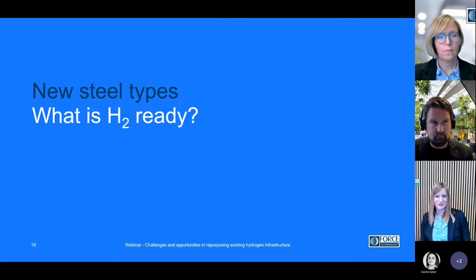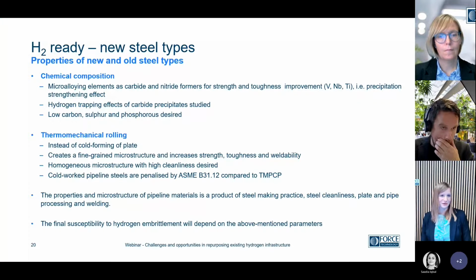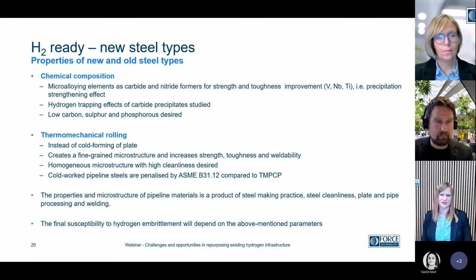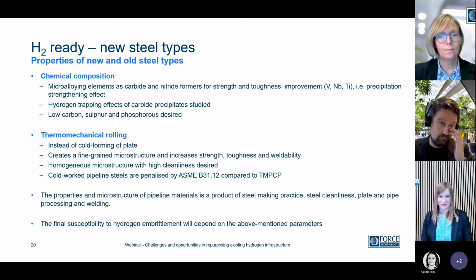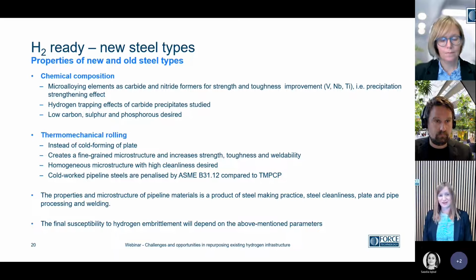But besides investigating use of low-cost materials, also new alloys are being developed for hydrogen applications. And we often receive the questions, what are these H2-ready steels, these new steel types? Well, it's basically a focus on chemical composition. So using microalloying elements, strong nitride and carbide formers, that would be vanadium, niobium, titanium, and these have a strengthening effect, but also a hydrogen trapping effect. And that's being investigated quite heavily and researched, because if you can introduce hydrogen traps into your steel, you know where hydrogen will go and collect, instead of collecting at a crack tip,